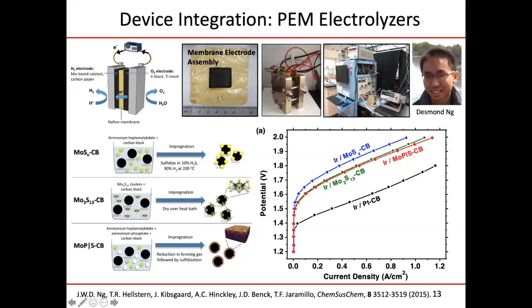It's only 5 square centimeters, where Desmond took a lot of these sulfides and phosphides and phosphosulfides, different transition metals, many that are not depicted here, really put them into ink formulations to start making devices and see how they would perform. So here's the current voltage curve. Now we're drawing 1 amp per square centimeter, which is a current density that is relevant for the commercial grade tech.